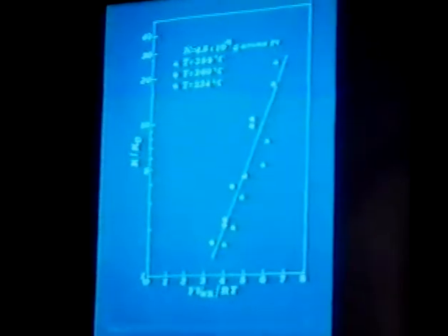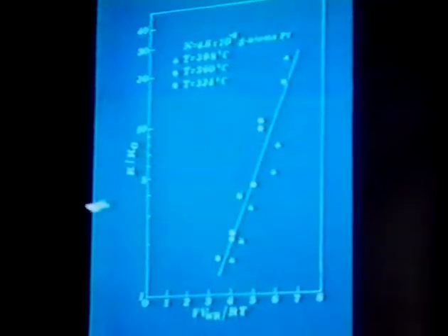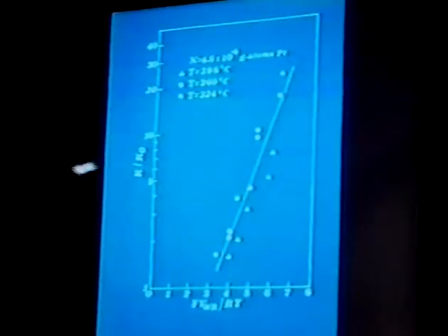However, the central finding of our work in this area so far has been that the important parameter for explaining the lambda effect and for describing it is not the current, but rather the voltage, the potential of the catalyst. And this is shown in this slide, where we plot the kinetic constant of ethylene oxidation on platinum under conditions where the reaction is first order in ethylene and zero order in oxygen, as a function of the catalyst potential VWR, which is the catalyst potential in relation to the reference electrode.